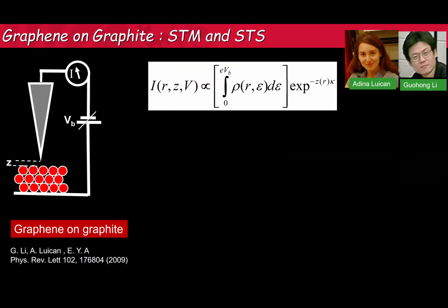So we said, okay, what is the perfect substrate for looking at graphene? And there is no more perfect substrate than graphite. So you put your graphene on graphite and it is perfect. And then you bring your STM and look at it. Now, the way a sample like this has to be prepared, your graphene sits on top of graphite, but the distance has to be a little bit larger than the equilibrium distance, which is about 0.3 nanometers. So when you just put it on top, or you did the inverse exfoliation trick, you exfoliate your graphite. Instead of looking at what's on your tape, you look at what's left behind. And sometimes you have flakes that are floating on top. And that we can find with STM. We see the steps, we see those flakes.